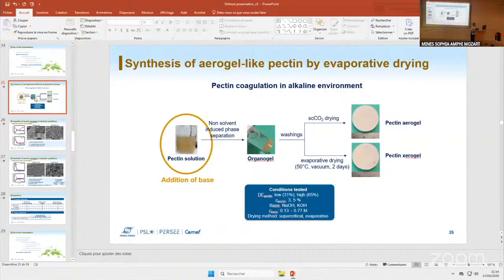So starting from the beginning, for the calcium and the gel structure, whenever we have cross-linking and gel formation before drying and not just coagulation, we have a sturdier structure. We know that for the exact same formulation of concentration, pH and non-solvent, when we have calcium cross-linking, we have less shrinkage during supercritical drying. However, this is not enough to avoid supercritical drying. There have been tests in previous studies, and by evaporation, at least in vacuum, they were not successful, even if they were calcium cross-linked.